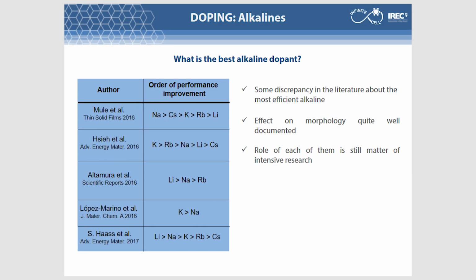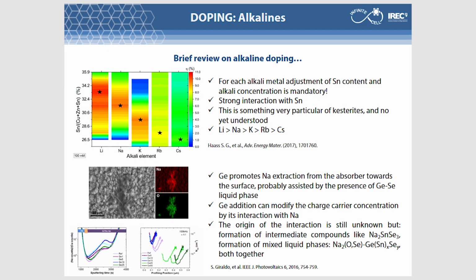I think the most important are the alkalis. So in terms of alkaline doping, there is first a controversy in the literature: what is the best alkaline? Some works predict sodium, others potassium, others lithium, and so on. During some time, people were confused about this until the works of our colleagues from EMPA showed that in kesterite there is a peculiarity: the alkaline element interacts a lot with tin. Then each alkaline element requires a different tin quantity. So the optimal quantity of lithium, sodium, and potassium doping also depends on the composition of your kesterite, explaining why different groups are obtaining different results. For example, if you are working with potassium, you need less tin than if you are working with lithium.